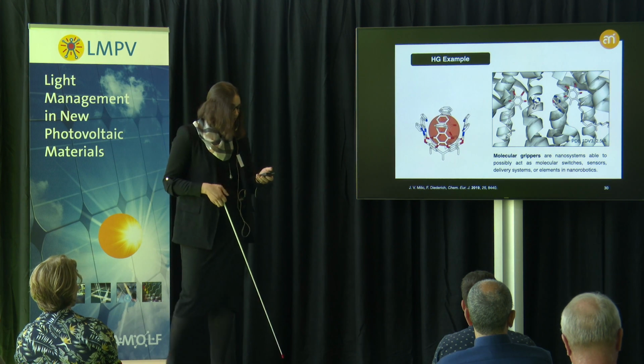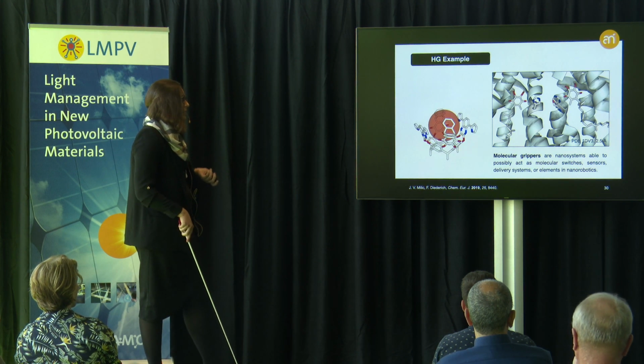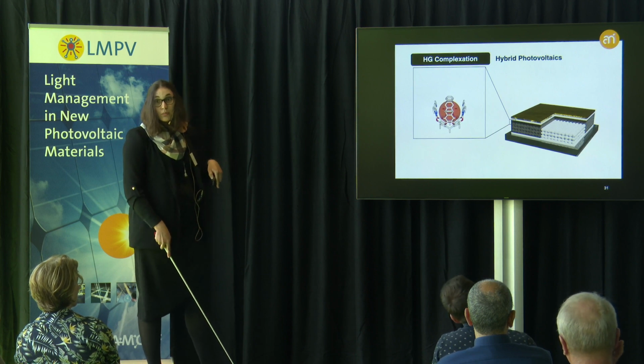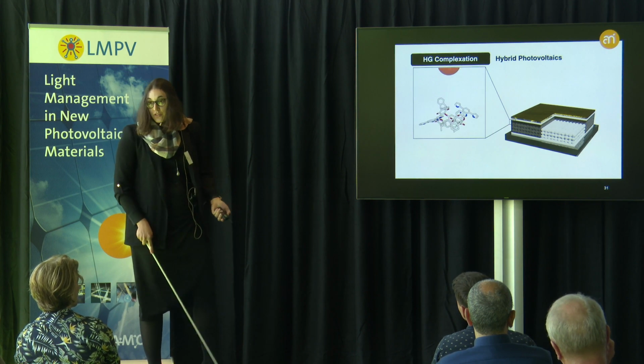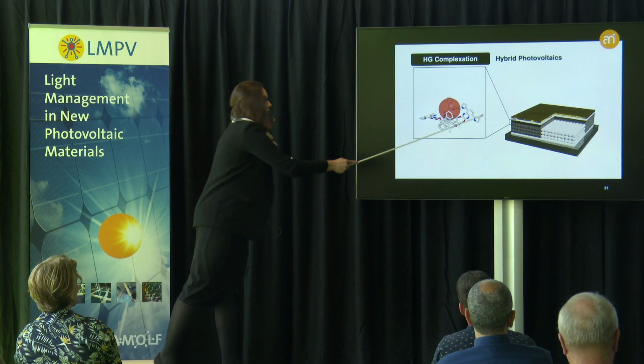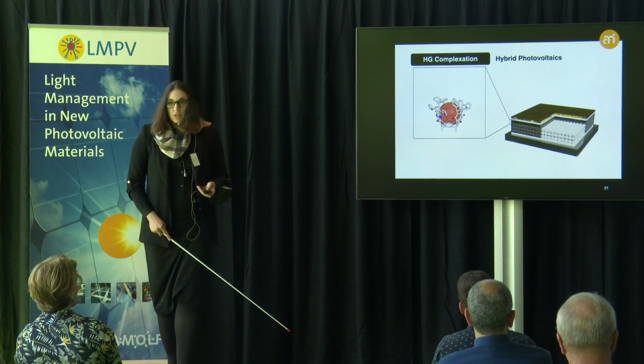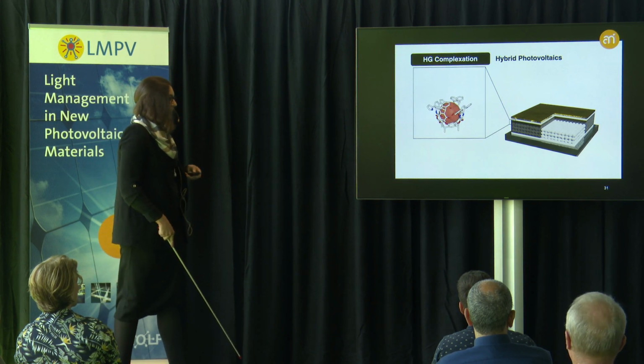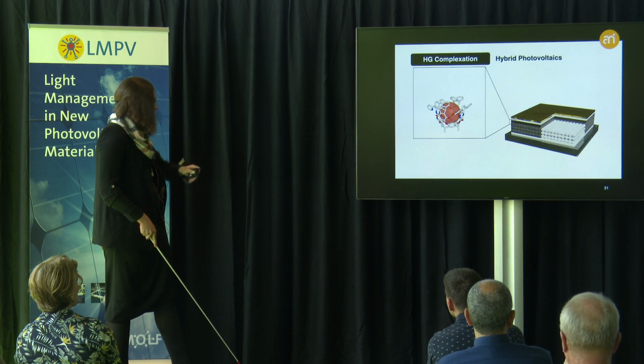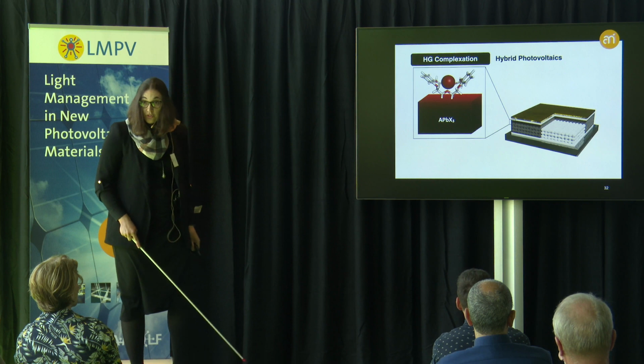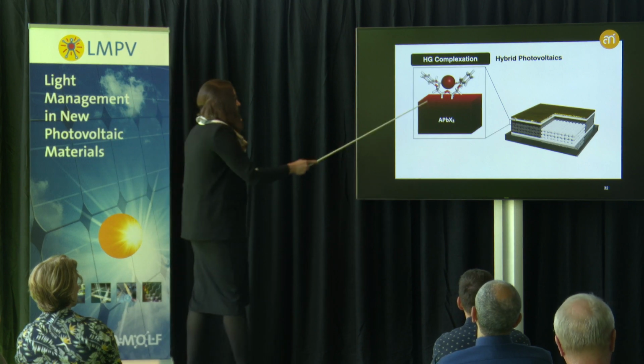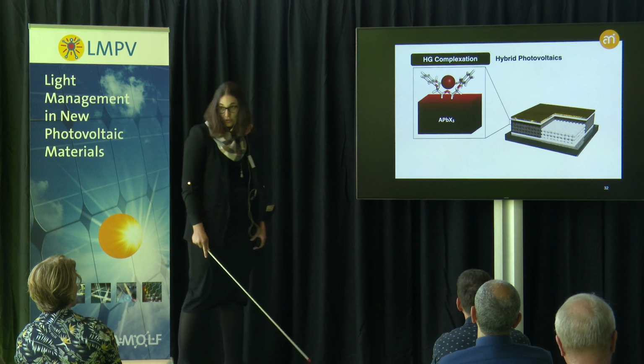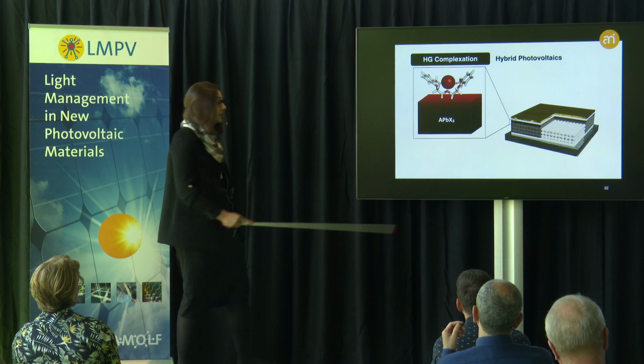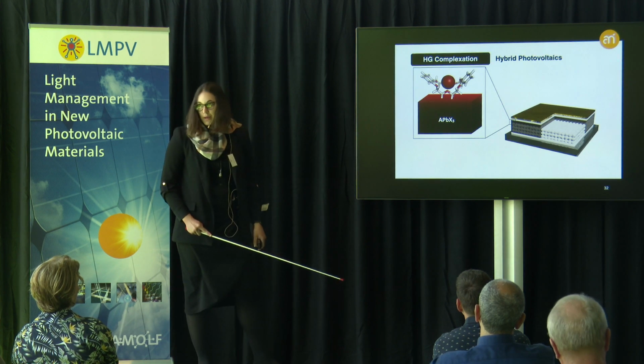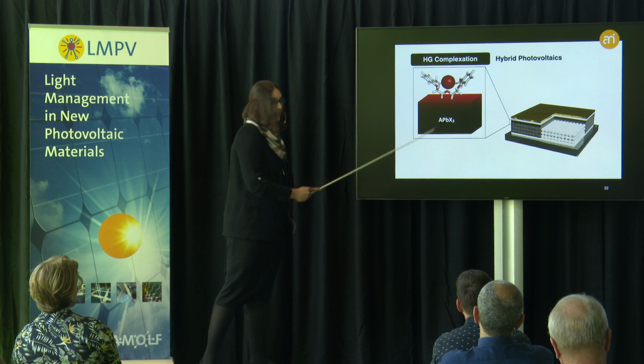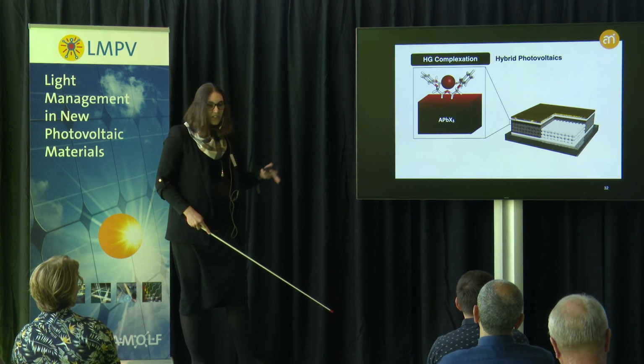Now, learning from and inspired by these systems, we've been asking ourselves, can we achieve some of these dynamic controls inside the hybrid perovskite framework by controllably binding and delivering specific ions inside the hybrid perovskite material, even in a functional device during operation? And to illustrate this, considering especially the complexity and the steric demand of these systems, we have looked into a number of macrocyclic potential hosts based on their geometric compatibility, primarily involving these relatively simple crown ethers that you see here, selected on the basis of complementarity with two specific defects on the surface of hybrid perovskites, which are uncoordinated A cations and lead cations.